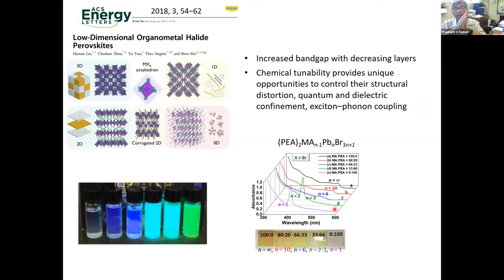Okay, so with that, now there is another area that has opened up in the perovskite. These are low dimensional organometal halide perovskites. From 3D, as I mentioned, in the A-site cation, you can play around with the A-site cation. If you have, instead of methyl ammonium, bulky ammonium ions like butyl ammonium or phenethyl ammonium in this case, you can break this 3D structure, basically slice it out. And depending upon the ratio of methyl ammonium and, say, phenethyl ammonium ions, you can control the layer thickness. That means how many layers of this.